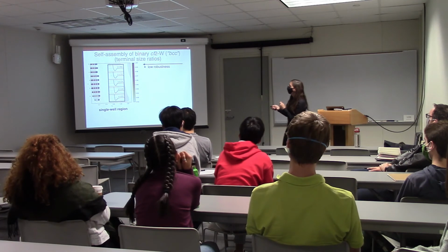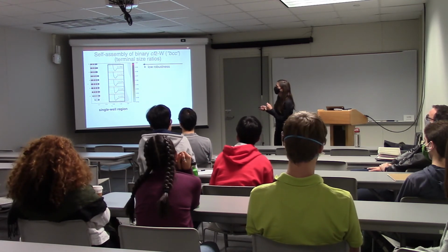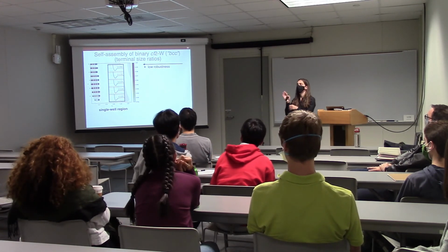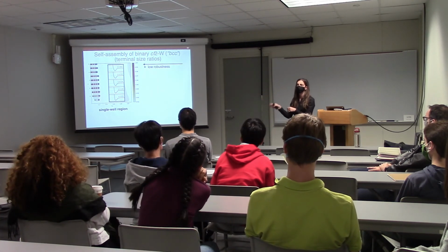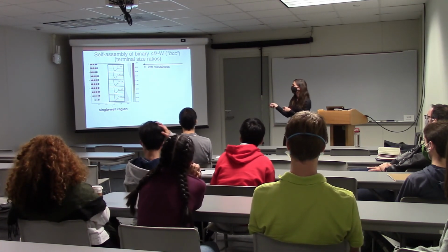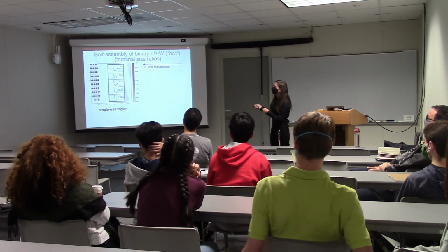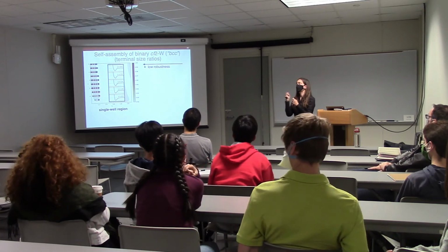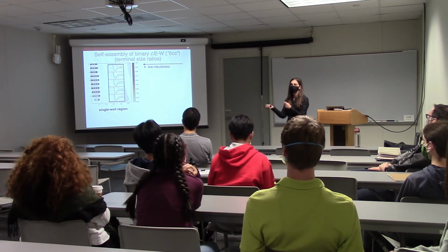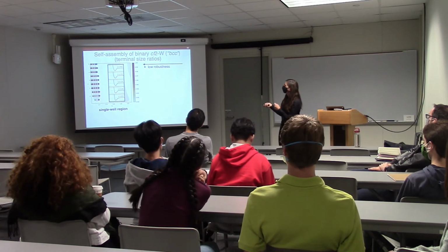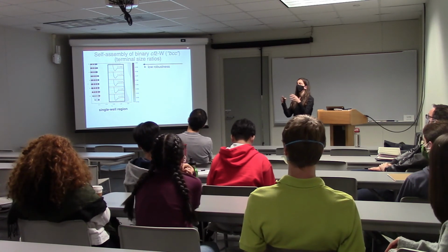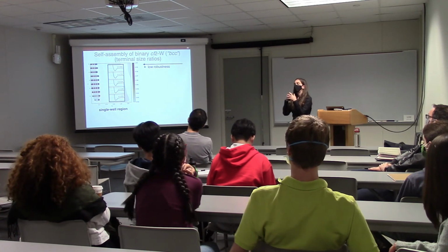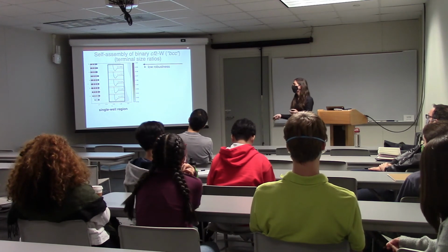size. So this is the terminal size ratio, which means, okay, one means that they're the same size, so if the structure doesn't form then we have a problem, because then that was never supposed to be BCC in the first place. But if it's like 99%, it means your particles are just a tiny bit different and already the structure formation breaks down. If it's around 92%, you can change your particle shape, particle size, quite a bit, and your system reliably forms the correct crystal structure.